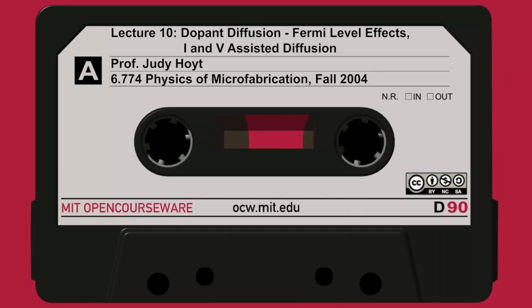So I do a diffusion experiment where I start with an initial profile, a Gaussian profile of boron, and I let it diffuse, all of it in a background concentration of high concentration boron 10. I measure the diffusivity. Now I take another sample, and this time I put a higher concentration of B10, again constant in space, but higher than in the previous sample. And what you see is that the diffusion of the low concentration dopant is more enhanced now. And you keep doing this, putting in this box-like profile as the background at higher and higher concentrations, and you measure each sample and its diffusivity.